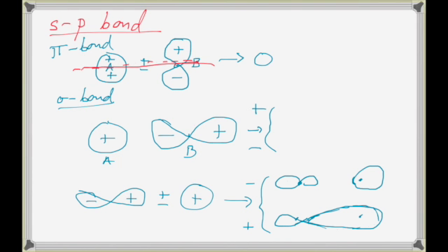It just depends on which side of the p orbital your s orbital is. But at any point, you still get a bonding, anti-bonding state. And when we talk about, you can look up these matrix elements in tables for the well-known semiconductors, and this would always be referred to as SP sigma. I don't know why they have to put the sigma, because there is nothing else. If you have an SP bond, it's a sigma bond, because there are no pi bonds.